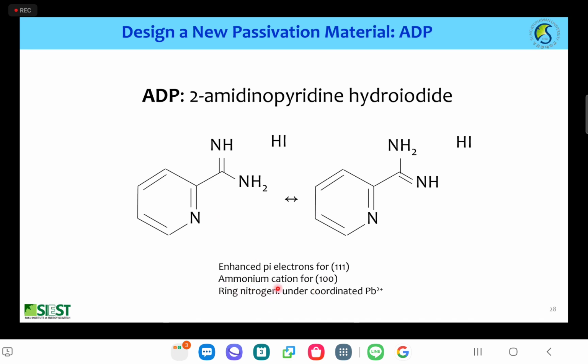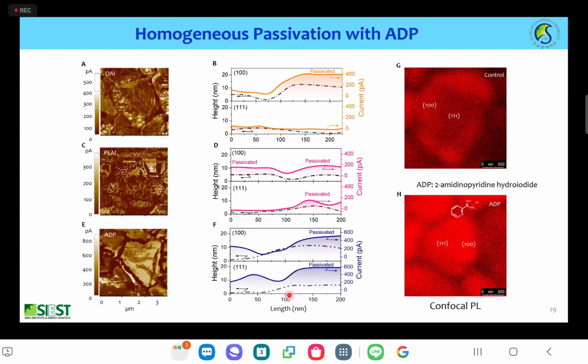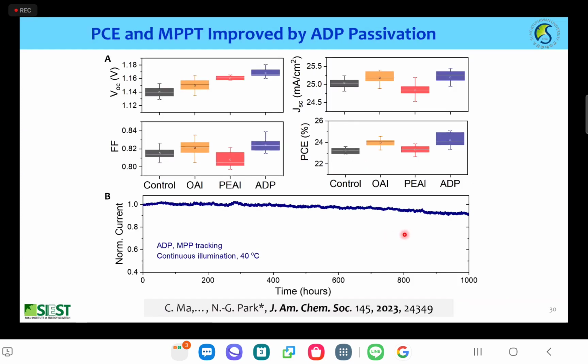And there is an ammonium cation, which is beneficial for the 1,0,0 crystal facet passivation. And then we included a ring nitrogen. This is for the passivation of the undercoordinated lead ion. By using this ADP material, after passivation, we found that the surface was evenly, homogeneously passivated regardless of the crystal facet. And then eventually we get higher efficiency using ADP passivation technology.